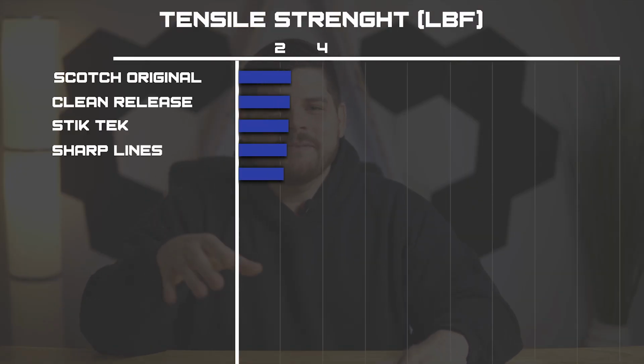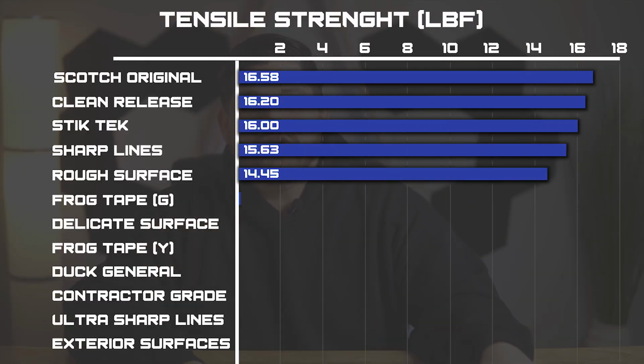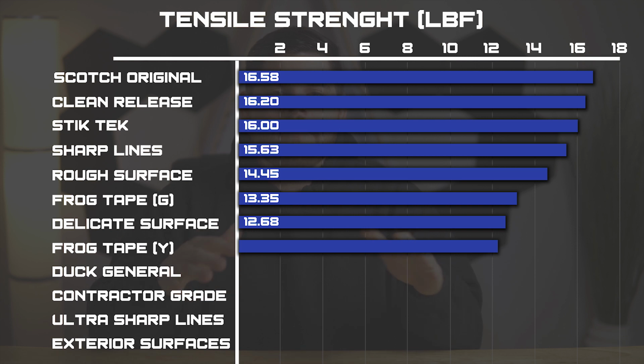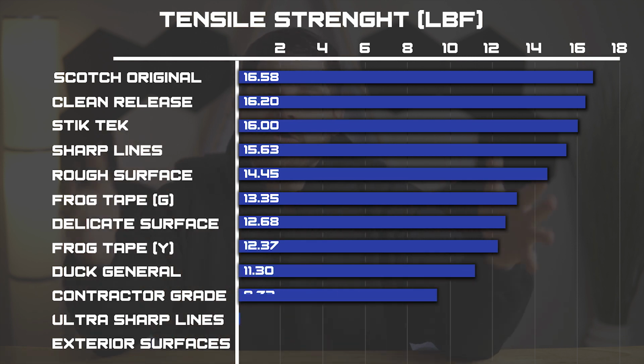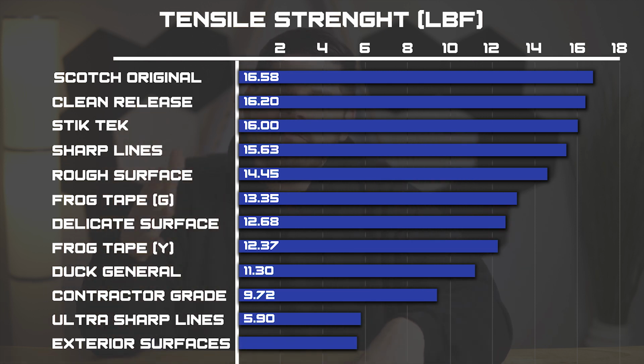The blue painter's tapes appear to be the strongest. The green frog tape comes in right at the middle of the pack. Both tapes intended for delicate surfaces come in pretty close to each other, and the masking tapes were below average. The Ultra Sharp Lines and the Scotch Exterior appear to be made of the same stretchy material, leading to a very low tensile strength but high flexibility.